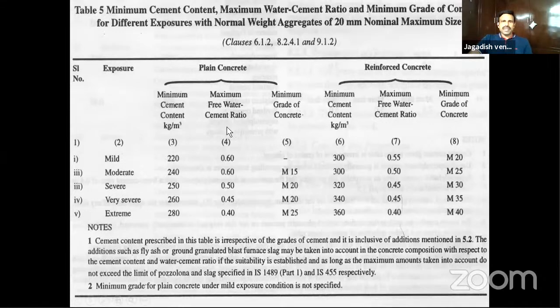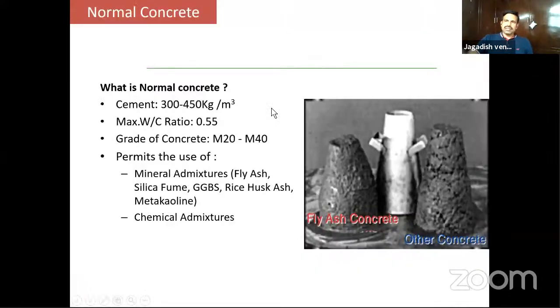With that, let me get into the sum up of the normal concrete. Typically, in cement, we use a quantity between 300 to 400 kgs per cubic meter of concrete. The maximum cement content allowed is 450 kg per cubic meter as per IS 456. Beyond 450 kgs, it leads to heat of hydration, cracking, and other factors will get affected.